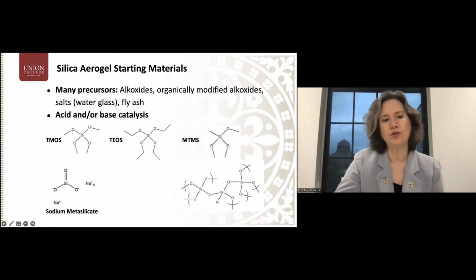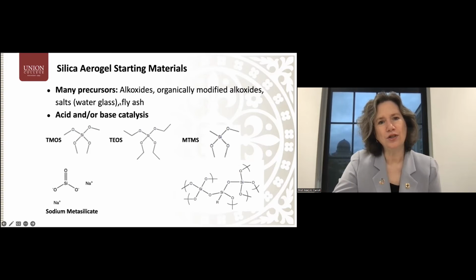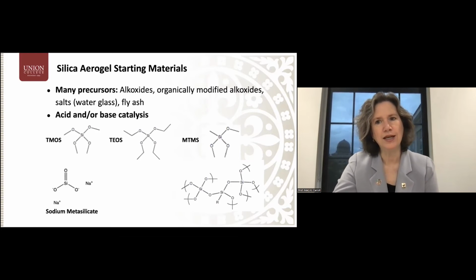You can also use salts, and you can also use certain types of waste materials that are high in silicates, including fly ash. And so for some of the applications in building materials that do not require translucency, a big advantage is that waste materials could be used to make these. And I didn't mention in the earlier process, but in order to do the hydrolysis reactions, you have to do acid and or base catalysis, which you choose changes somewhat the optical properties because it'll change some of the microstructural way that it forms. But there's lots and lots of literature on silica sol gels and silica aerogel materials.